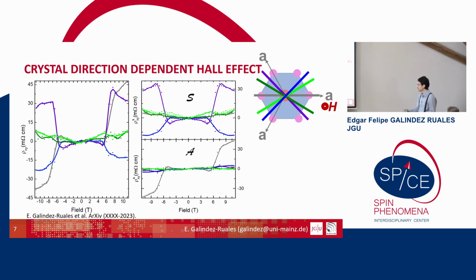I promise you more details of all the measurements next week, when the paper will be out with an arXiv code. For now, you can just discuss with me. So the symmetry of the signal follows the symmetries of the crystal. We have a fully symmetric signal when you have iron, oxygen, iron, and you have a fully antisymmetric signal when you have iron and then another iron here. That's quite curious, and that can only be explained by the altermagnetism that Libor explained.